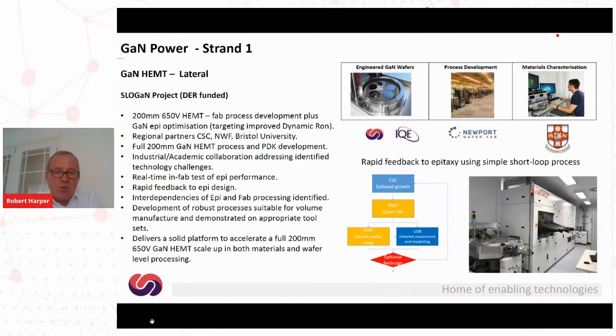So the way that this is working is that we're growing the materials at IQE, so these are 200 millimeter gallium nitride on silicon wafers, and we're then processing those at Newport Wafer Fab and assessing the electrical performance of those wafers with respect to the dynamic R-on characteristics. And this is a short loop process.